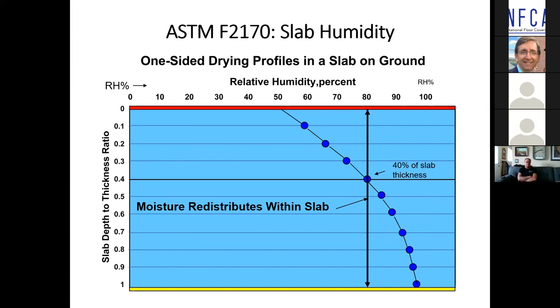The research that was done at Lund University, headed up by Göran Hedenblad, who has numerous published articles on the subject, found that where the moisture gradient and the redistribution lines intersected always fell at approximately 40% of the slab thickness. So what does that mean? It means that if you take a 5-inch slab, 40% of 5 inches is 2 inches. You take your relative humidity test 2 inches down in a 5-inch slab, it is the predictor of what the redistribution moisture level will be once the slab is covered. So it's a great predictor of what's going to happen to the moisture level in your concrete after it's covered.